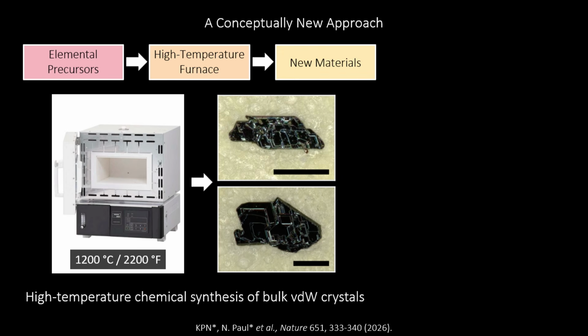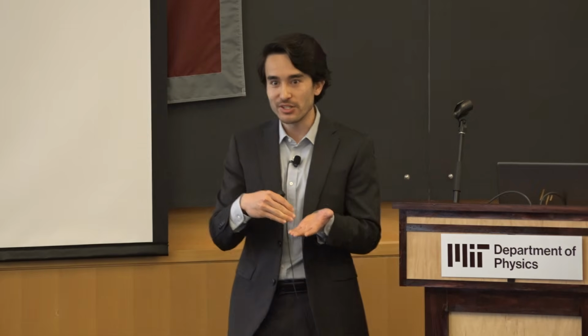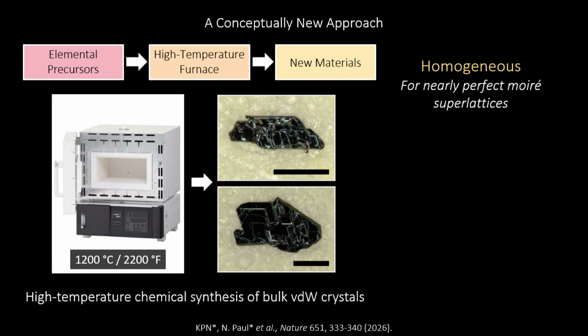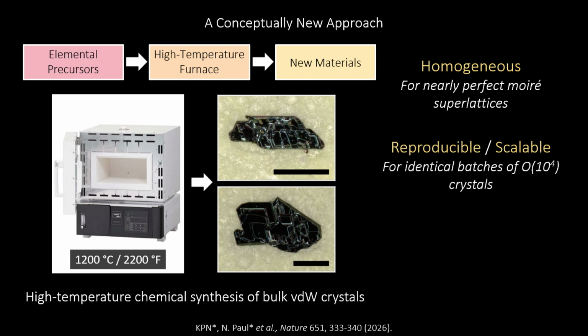So the idea is we're going to take some elemental precursors that we can buy online. We're going to react them in high-temperature furnaces like this one that gets up to 1200 degrees Celsius. And we're going to grow van der Waals crystals, new materials. These are layered crystals that have Moiré superlattices built into their layers. And so the key advantages of an approach like this is first that the Moiré superlattices that we can stabilize are going to be highly homogeneous because we're stabilizing them deep within thermodynamic equilibrium. In addition, because we're growing these crystals in big batches, this represents a potentially scalable route for generating Moiré materials for next generation electronic technology.